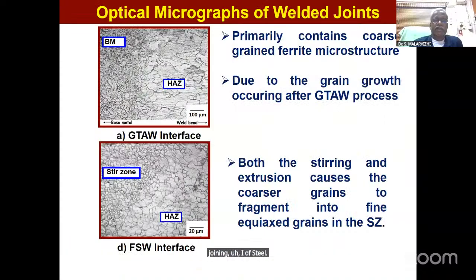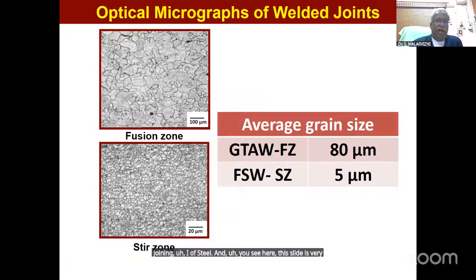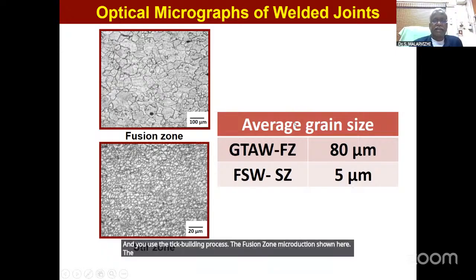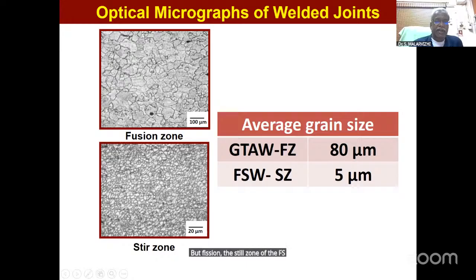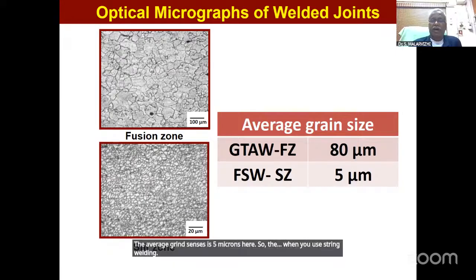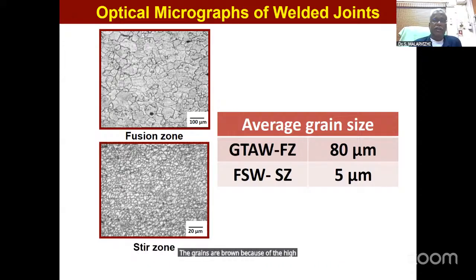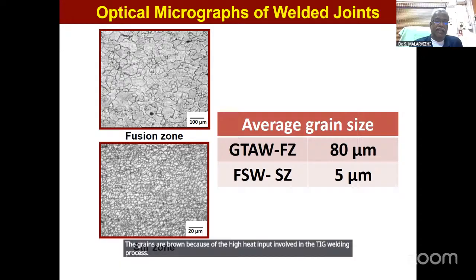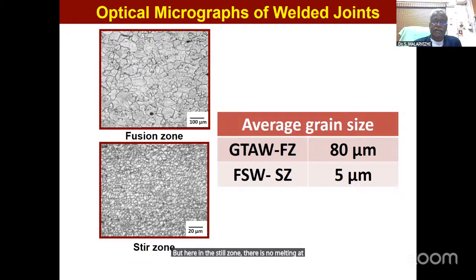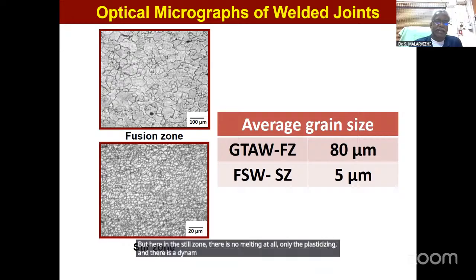And you see here, this slide is very important. The top one is the fusion zone. When you use the TIG welding process, the fusion zone microstructure is shown here. The average grain size is 80 microns. But in the stir zone of the FSW, you see the grains become finer. The average grain size is 5 microns here. When you use TIG welding, the grains are grown because of the high heat input involved in the TIG welding process. But here in the stir zone, there is no melting at all, only plasticizing, and dynamic recrystallization takes place. Because of that, grains become finer and finer here.